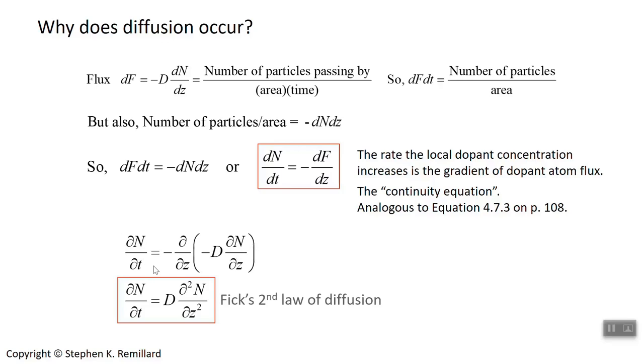The time rate of change of the concentration is minus d by dz times minus D dN by dz. That's then cleaned up a little bit here. Minus sign is canceled. D comes out. It's a constant. And you have Fick's second law of diffusion, which tells you that the rate that carrier concentration is changing is proportional to the concavity of the concentration gradient. Those are two key laws of diffusion, the first and the second law of diffusion.